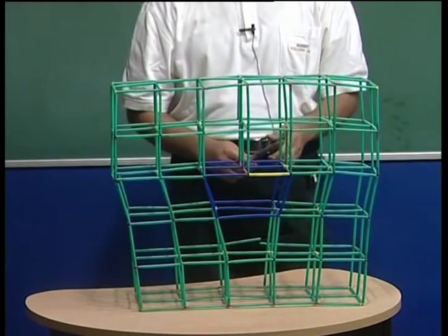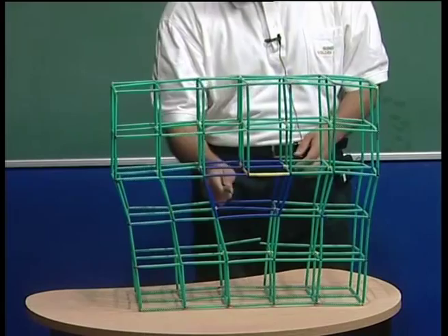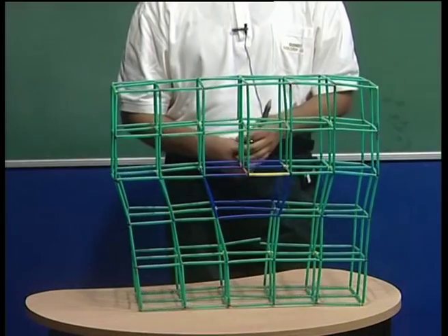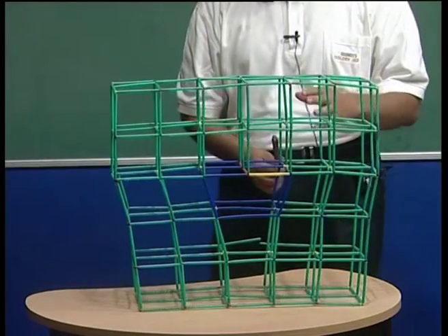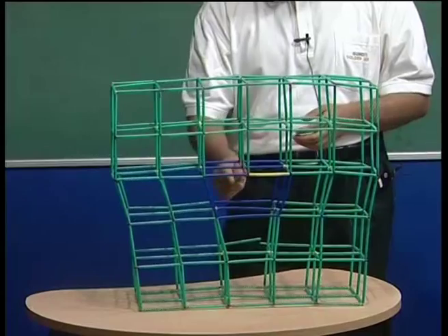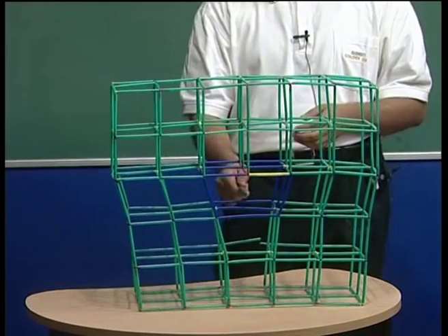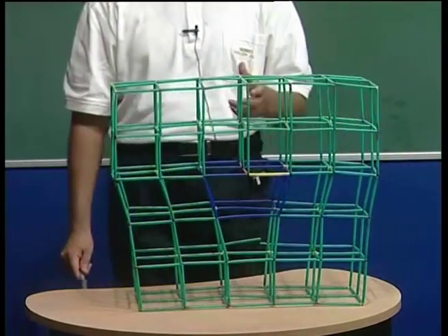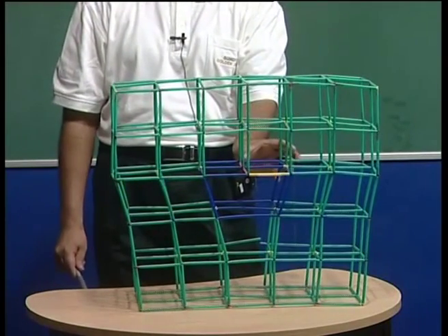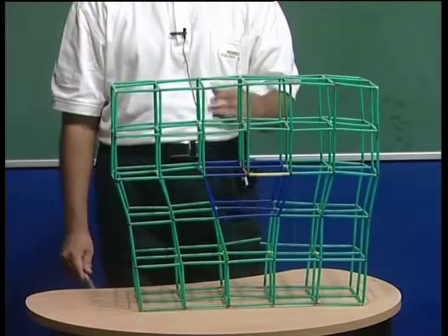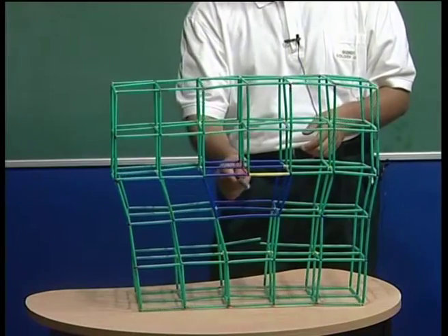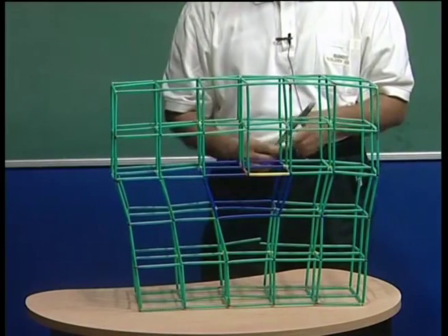graphics later on. The other point we noted using this model, which is very clear, is this region, for which we shall use the word core. Technically, the core is the region where the linear elasticity theory breaks down. That means the deformations are so large that you cannot use the linear elasticity theory anymore, and this region associated with some free volume is known as the core of the dislocation. Typically the core of the dislocation is a region of about a few Burgers vectors. In some cases it could be a Burgers vector, it could be about 5 Burgers vectors, but some region of the order of a few Burgers vectors. And this free volume, as we shall see later, is very important in certain phenomena which we shall consider.